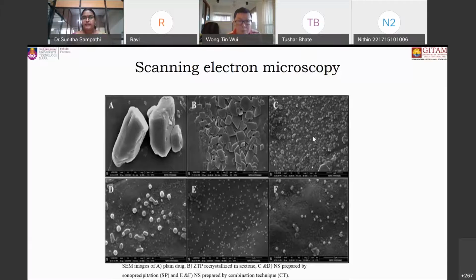And here you can see the particles are discrete. They are converted to spherical shape. And the particle size with the sonoprecipitation technique was around 200 to 270 nanometers. And all the particles are spherical and individual, they are not agglomerating with each other. And in the case of the combination technique, the particle size has been reduced still further because of the principle involved in high pressure homogenization, which is based on the cavitation as well as impaction forces involved in the technique.